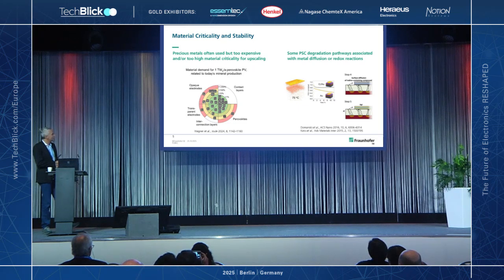and you can find, well, of course, that noble metals like gold are a no-go. They are just too scarce, and also, of course, very cost expensive, so you cannot use these for opaque electrodes. And, of course, indium is sometimes an issue. What was a bit surprising is that also cesium can be an issue if you work with cesium-containing perovskites. This is not because we have so little cesium in the world, there's enough of it, but it's just a matter of how much is currently being produced or mined, which could lead to material criticality issues.